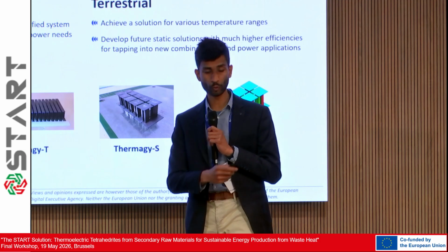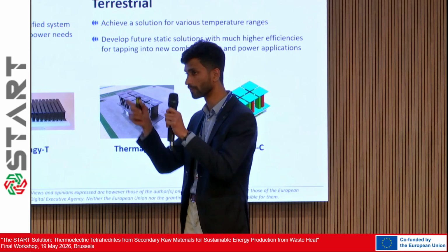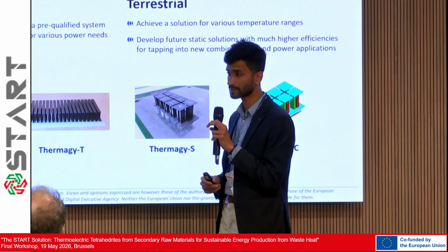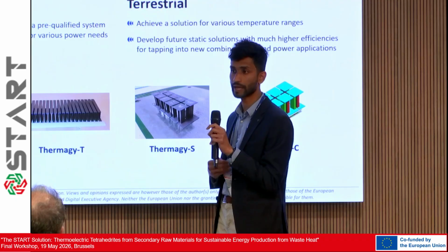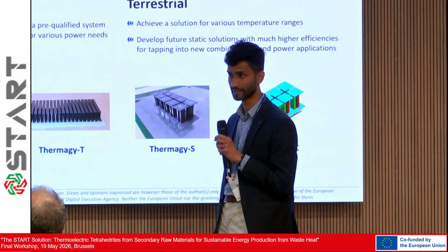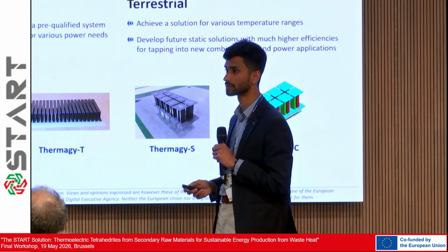Okay, thank you. And do you have any special protective coating, especially for the magnesium-based material? No. We had done some coating analysis beforehand at the material level, and eventually we saw that you form this oxide layer regardless. And we have noticed that it might not be as harmful in the end, that it could also be its own coating. So eventually we decided to simplify that and just use it in air. Okay, thank you.